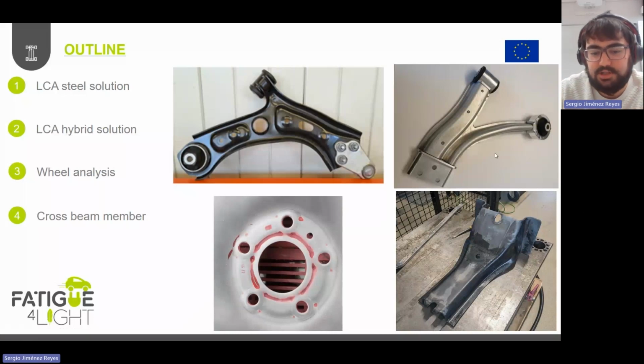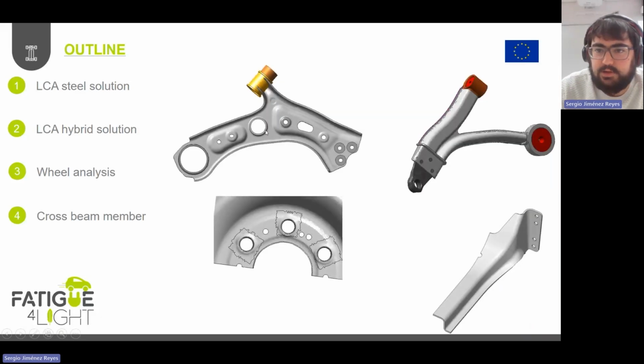And in order to do that, what we've done is just using the formulation that I've presented you previously. So here you have the 4 demonstrators that we've been studying experimentally: the lower control arms, the steel and the hybrid solution, a wheel, as Lucia mentioned at the very beginning of today's webinar, and this cross-beam member used in the heavy-duty electric vehicles. So the first step was converting these real demonstrators into the numerical models that you can see here. Of course, we take advantage of the symmetry conditions in the wheel and in the cross-beam member when possible, and then we start with the numerical simulations.